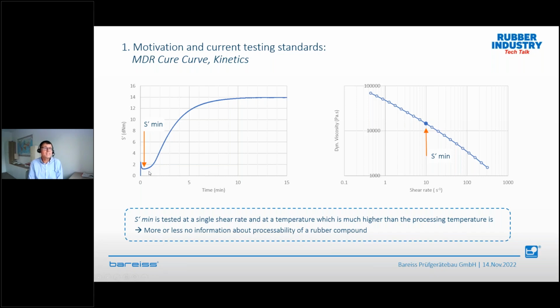What is the reason? The reason is easy to explain, because although the minimum curve is done at one shear rate, normally we are running at 0.5 degree of arc and at a frequency of 1.67 Hertz. So that means also here we are at one shear rate. So you have no information what happened at lower shear rate and what happened at higher shear rate. And the second one is normally we make cure curves at 180 degrees Celsius, which is far away from the processing temperature. For example, when a material is coming out of an extrusion line, we are between 90 and 110 degrees Celsius. And so you should not expect, when you measure only at one shear rate and at a different temperature, which is far away from your processing temperature, that this will give you information about the processability of a rubber compound.